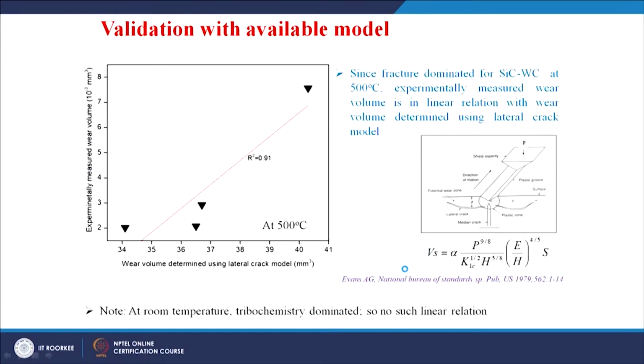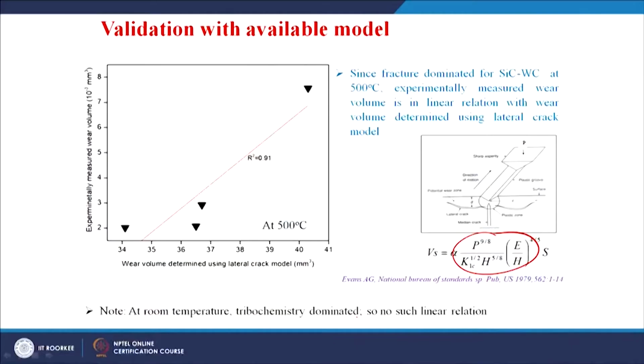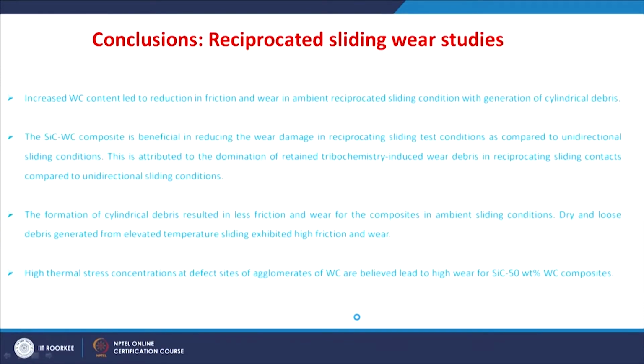We also validated the experimentally measured wear volume with the wear volume determined using a lateral crack model. Since fracture dominated for the silicon carbide tungsten carbide at higher temperatures, the experimentally measured wear volume is in linear relation with the wear volume determined using the lateral crack model. But at room temperature, because the tribochemistry dominated, no such linear relation is observed. So, this also indicates mechanical fracture at higher temperatures, whereas tribochemical wear at lower, room temperatures.